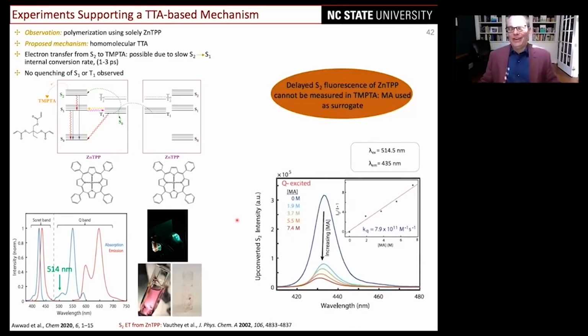And then finally, we use methyl acrylate as the surrogate, as I told you, because it won't polymerize. And again, just looking at the static quenching of the S2 fluorescence in this as a function of concentration very clearly feeds us back the same data we got from the time resolved experiment. So again, just dynamic quenching, but it's ultrafast quenching, which I will tell everybody, I wasn't the first to come up with this either.